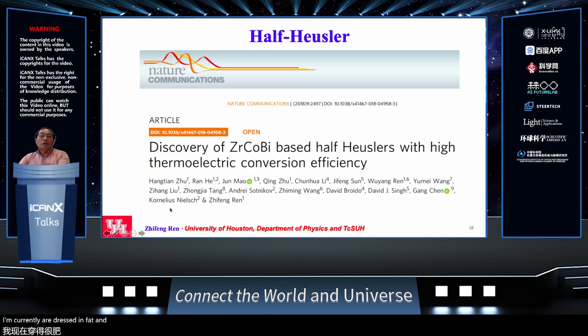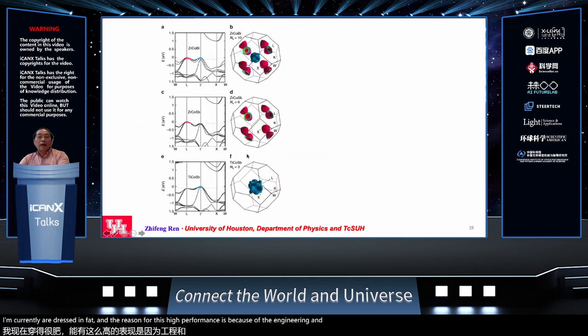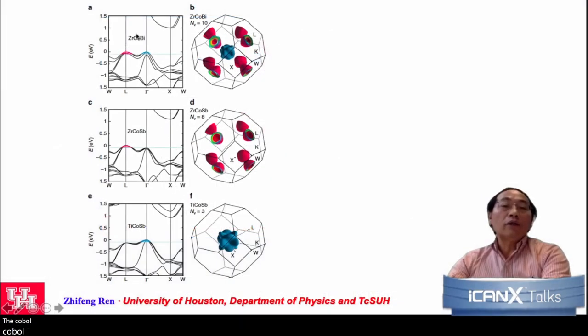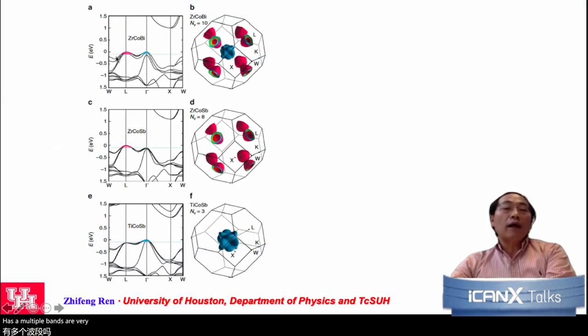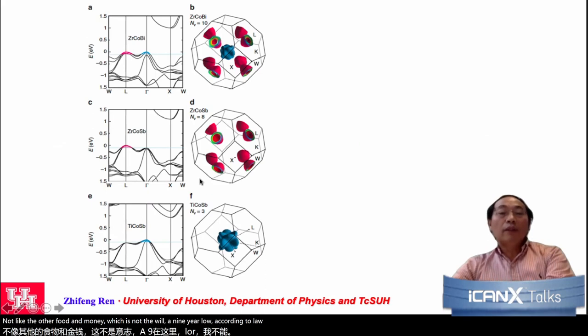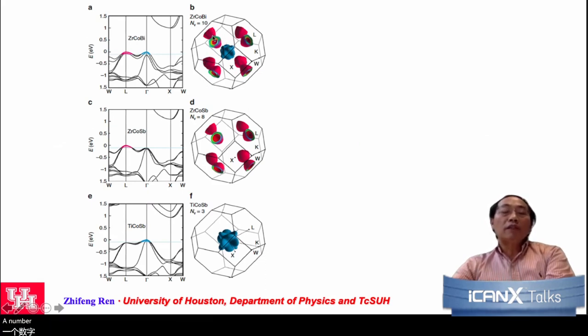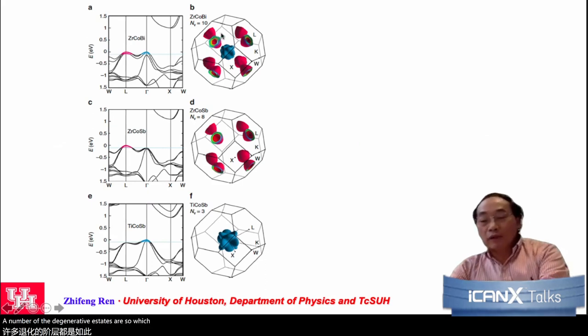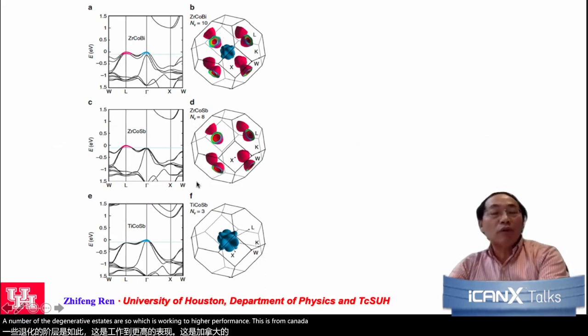And the reason for this high performance is the engineering of the band alignment. Zirconium cobalt bismuth has multiple bands very well aligned at the edge of the valence band. Not like zirconium cobalt antimony, which is not well aligned here, nor titanium cobalt antimony. Because of this good alignment of the band edge, we have many more degenerate states, which will give you higher performance. This is from the calculation point of view.